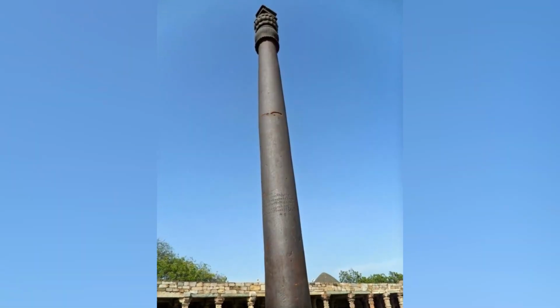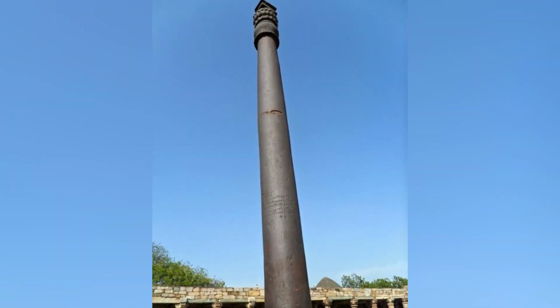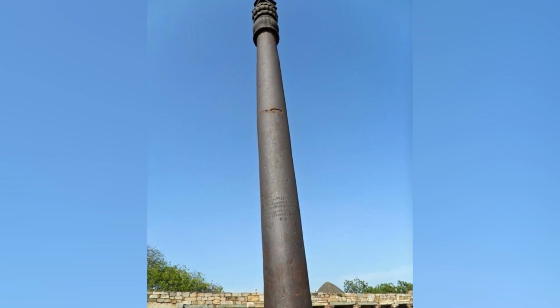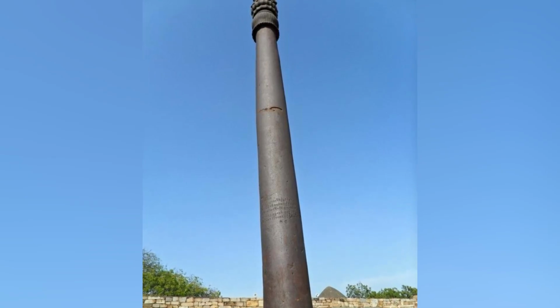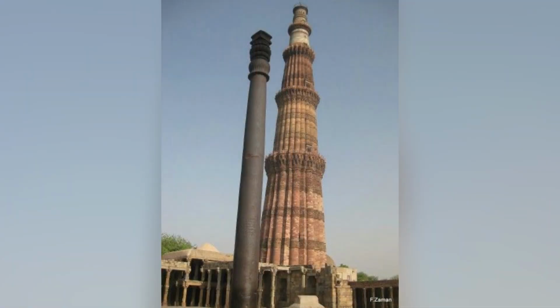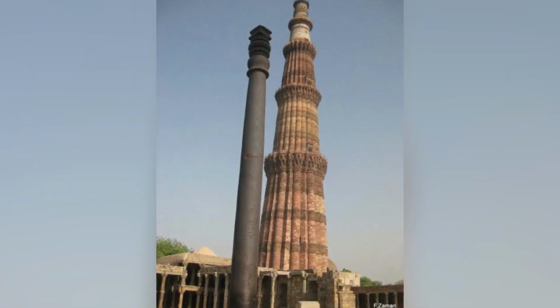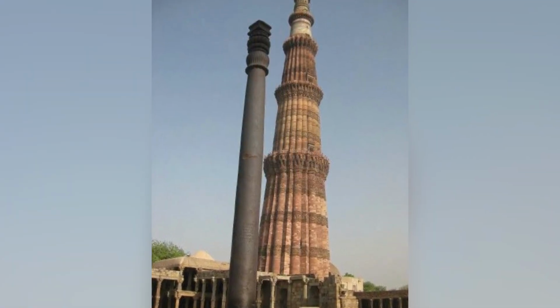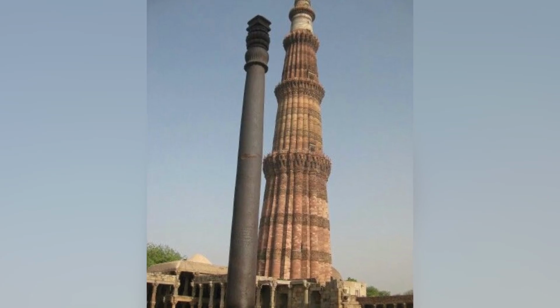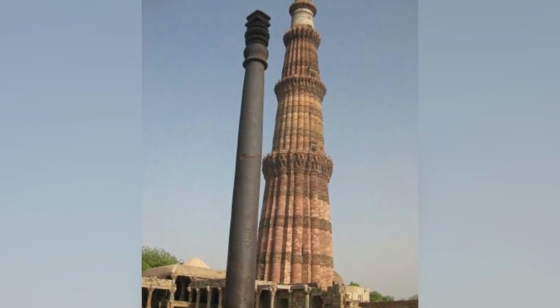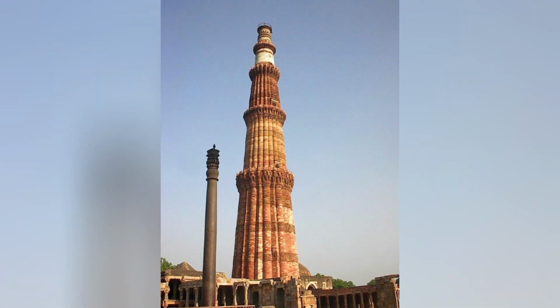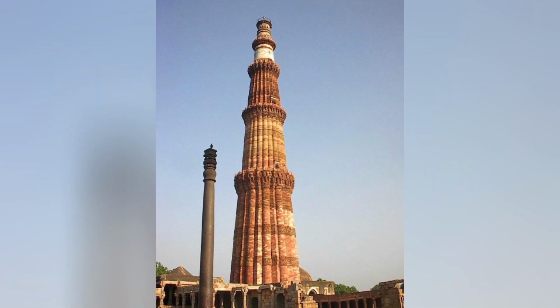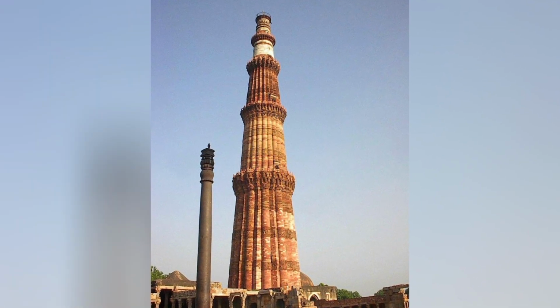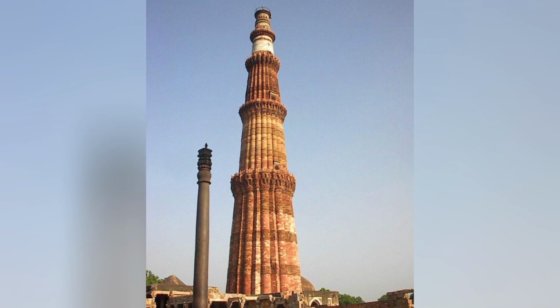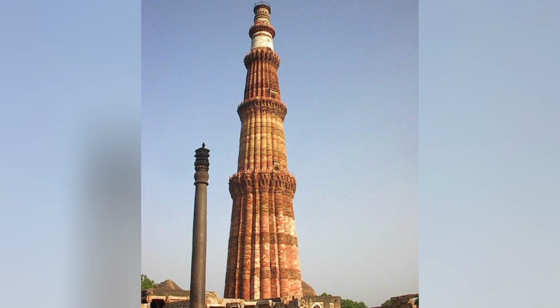protective film. The detailed chemical analysis of the protective film on the Delhi pillar has been conducted using a battery of modern analytical techniques that have provided information about the composition, the structure, and the properties of the film at multiple scales. The X-ray diffraction analysis of the film has identified the primary crystalline phase as iron hydrogen phosphate hydrate, with smaller quantities of iron oxide and iron oxyhydroxide.